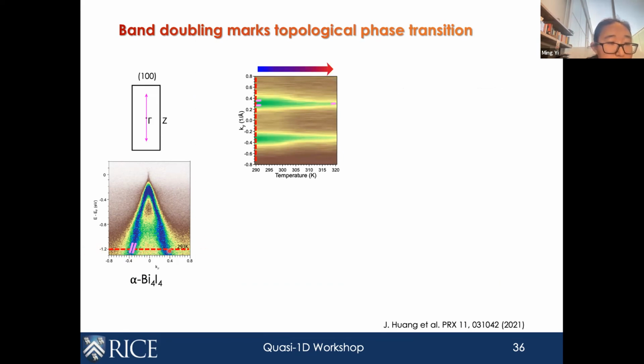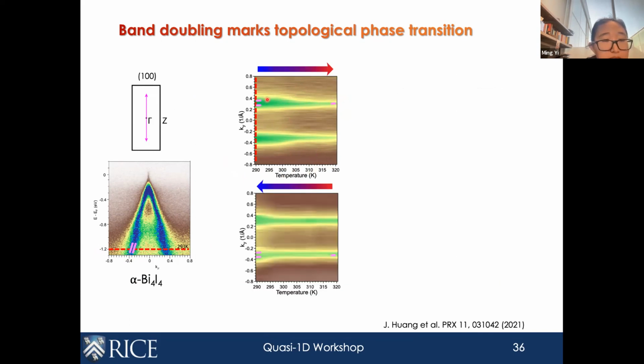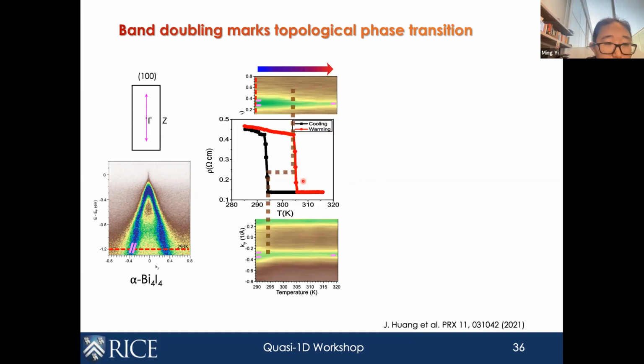And these two peaks are shown here, and you can see that across this transition around 300 Kelvin, you can clearly see the width of this peak actually become sharper as you go to higher temperature. This is definitely not a thermal effect. This is consistent with the transition from a two-layer unit cell to a single-layer unit cell. And then we can also capture the hysteretic behavior of this first-order transition by warming up and cooling down. And that hysteretic behavior is really consistent with the resistivity measurements shown here.